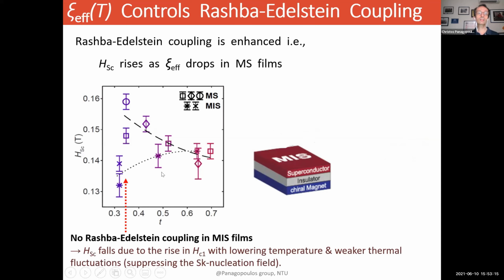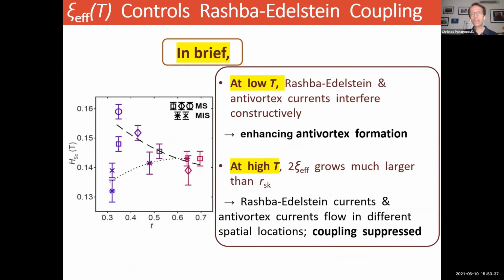And you can see here that the field where the superconductor first responds to the nucleation of skyrmions drops due to the rise in the lower critical field of the superconductor as I lower the temperature. And there is a weaker thermal fluctuation and therefore suppressing the skyrmion nucleation field. So in brief, at low temperature, Rashba-Edelstein and anti-vortex currents interfere constructively, and this enhances anti-vortex formation. Whereas at high temperatures, the 2 psi effective, that is the effective superconducting coherence length in my superconductor with my platinum, grows much larger than the size of the skyrmion. And therefore, Rashba-Edelstein currents and anti-vortex currents flow in different spatial locations. And therefore, this Rashba-Edelstein coupling is suppressed.